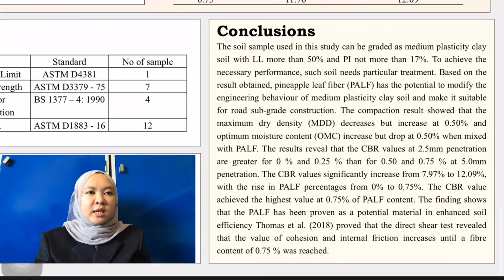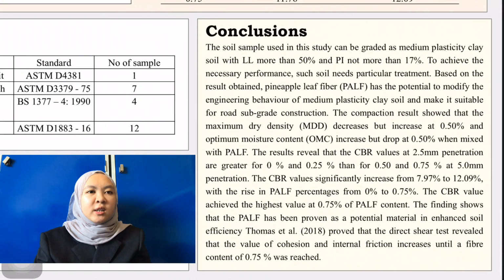As a conclusion, the influence of pineapple leaf fiber combined with problematic soil was explored in this study, which also analysed the clay soil characteristics and concluded the analysis on Pagoh soft soil. It can be concluded that the objectives of this study have been achieved with successful findings. The CBR value achieved the highest value at 0.75% of pineapple leaf fiber content.